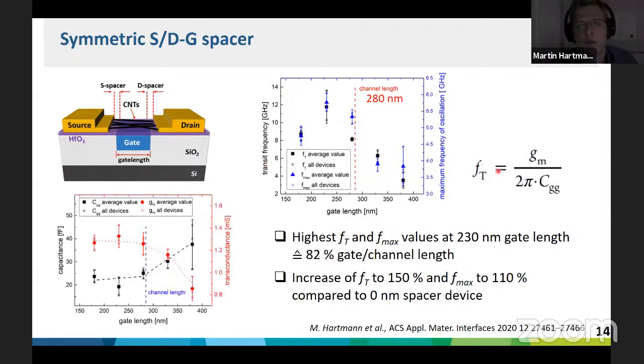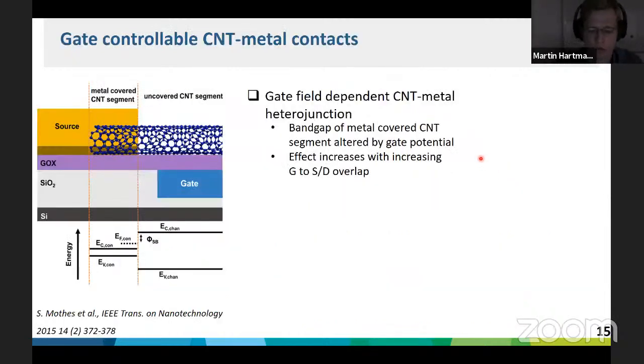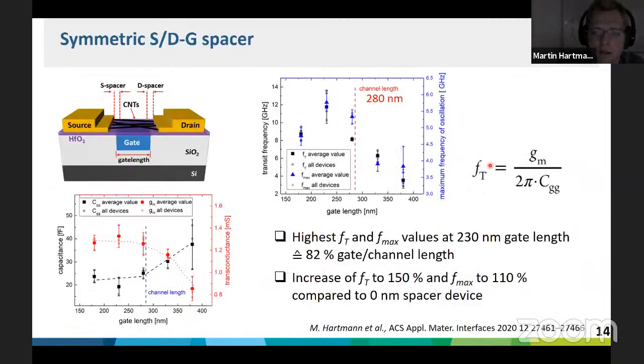With a rather easy formula, sorry for that, you can correlate the transit frequency to the transconductance of the device and to the total capacitance of the device. To understand this behavior in more detail, we analyzed the capacitance and the transconductance, the gm values. The capacitance trend was as expected. Without an overlap, you have an almost constant, maybe slightly increasing capacitance, and for an overlap, the capacitance increases strongly.